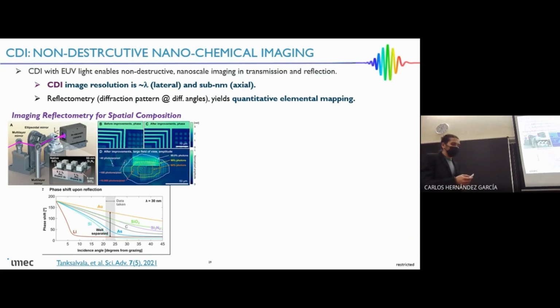Our goals here are to develop two different kinds of CDI. One is imaging reflectometry. This is where you collect diffraction patterns from a sample of interest over a variety of angles. Then you exploit either the phase shift or the changes in amplitude for different materials as a function of increasing incidence angle. In some regions, if you have a certain sample, you can actually get well-separated values for the phase or for the amplitude of different materials. And this allows you to do chemical imaging.